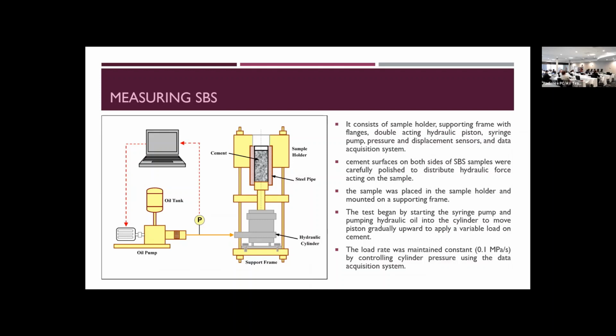The shear bonding strength was done by using a setup like this, which was specifically designed for the small samples. We are using the push-out method, as I presented earlier. As you can see here, the cement was poured inside of the pipe. And I insist, one of the reasons for that is that we have a very controlled contact surface between cement and the pipe, and that's the reason we prefer this method very much compared to other methods that have been used in the past.